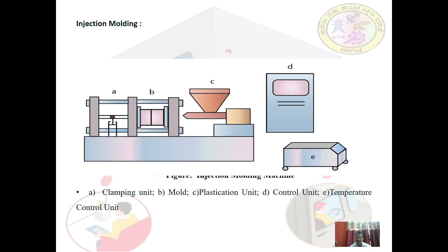After the injection phase, the holding pressure stage follows. It reduces the volume losses due to the cooling of the melt and thus avoids marks and voids in the molding. After this, the molding is cooled sufficiently so that it is dimensionally stable for ejection.